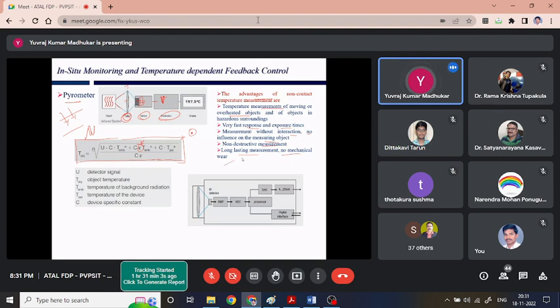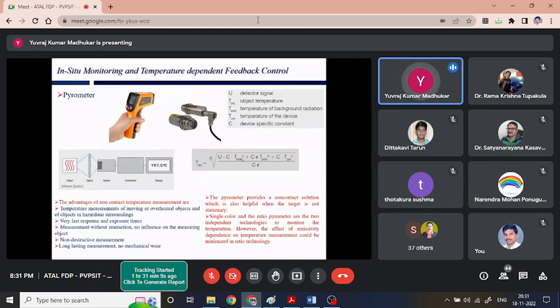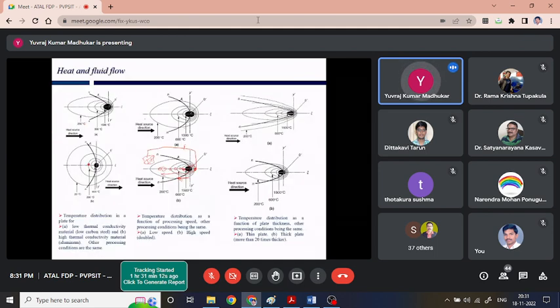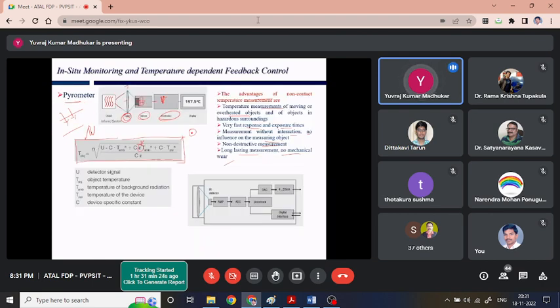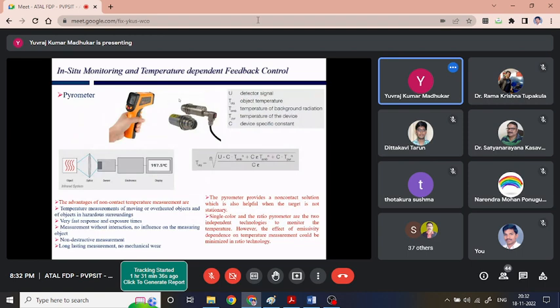However, because of this emissivity, since the emissivity of the material changes with the temperature, and here we are talking about a very dynamic process in which we are melting the wire and depositing it. Here the temperature is certainly going to be very much fluctuating. And since the temperature is fluctuating, the emissivity of the body, being a function of temperature, is going to fluctuate significantly, which is possibly going to give us a lot of errors in temperature measurement. So this pyrometer provides a non-contact solution, which is also helpful when the target is not stationary, when it is moving.